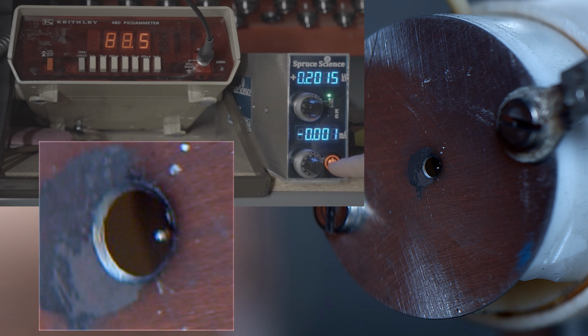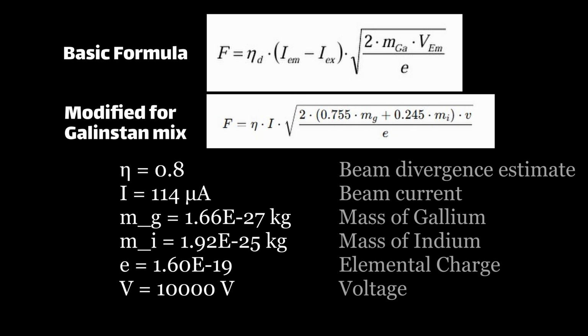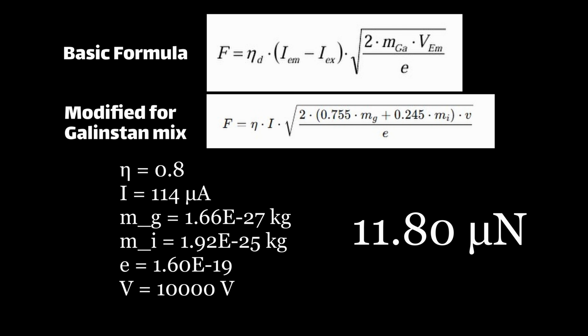Current on this one maxed out around 114 microamps, which if we run the numbers, works out to around 11 micronewtons. This includes a few assumptions like beam divergence and ion charge and ignoring any secondary electrons generated at the Faraday cup and stuff like that. But as a rough measurement, it should be pretty close. So there you go. 2 months of work and I've generated about a milligram of force.